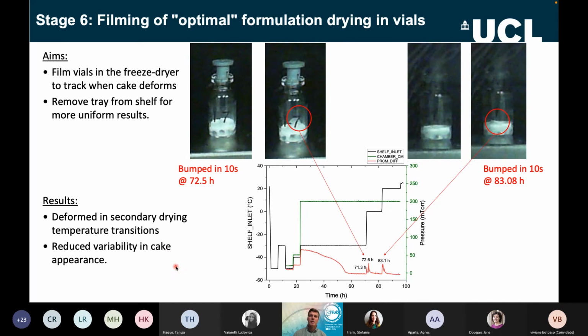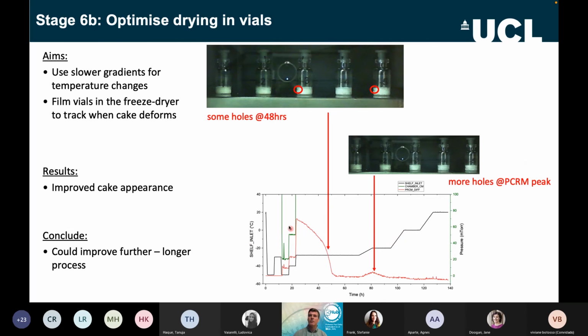So we figured maybe the thing to do now is to make it a little bit less extreme. So we did it again, and this time put in slower gradients, so it wasn't quite as abrupt. And you can see that means you get less of a spike in the water drawn off, more of a slow hill. And that indeed did improve the cake appearance. We still got some bumps and holes, but it was a lot better. So we could just smooth it out and improve the cake appearance without changing the formulation. So hopefully without changing the titer.